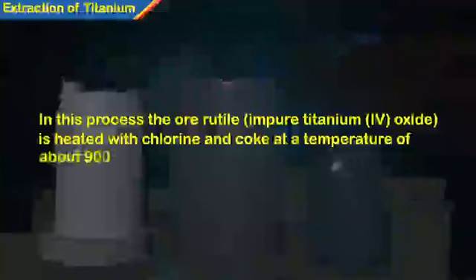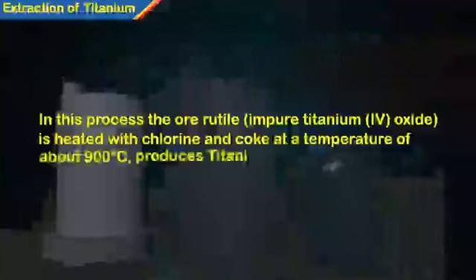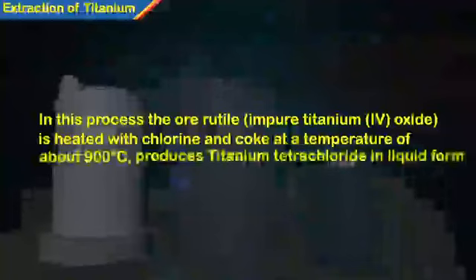In this process, the ore rutile, impure titanium IV oxide, is heated with chlorine and coke at a temperature of about 900 degrees Celsius, which produces titanium tetrachloride in liquid form. The pure liquid titanium tetrachloride can be separated by the fractional distillation process carried out in the presence of argon or nitrogen atmosphere. Reduction. This pure liquid titanium tetrachloride and molten magnesium are taken in a boiler and heated.